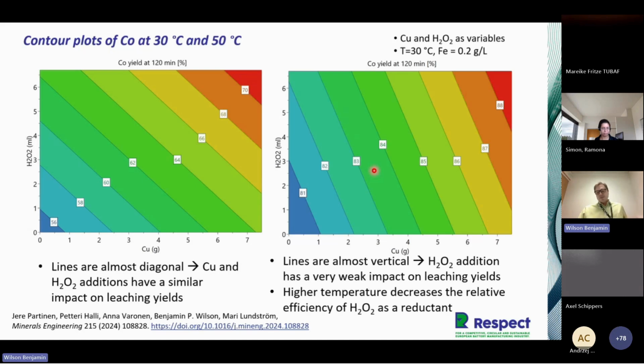And this is not a surprise, as higher temperature is known to decrease the relative efficiency of hydrogen peroxide as a reductant. So if you increase the temperature, the peroxide can break down rather than reduce the cobalt or the NMC. It can actually just break down due to the temperature effects as well.